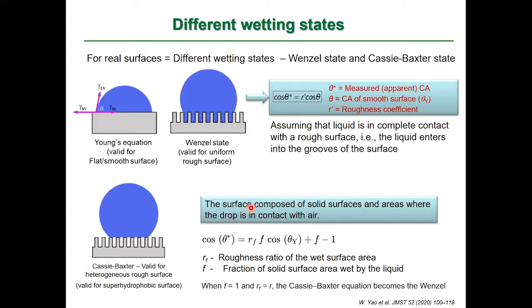So it considers the air pockets. The surface now is composed of solid surfaces and areas where the drop is in contact with air. Here they consider the fraction of solid surface area wet by the liquid and the fraction not wet by it. So the air fraction is considered, and this model is valid for superhydrophobic surfaces.